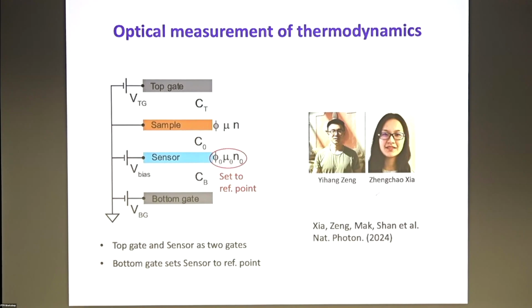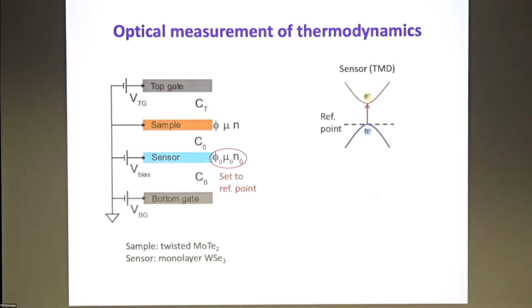In this kind of structure, we can think of the top gate and the sensor as acting as the top and the bottom gate to the sample. And the function of the bottom gate is to fix the sensor to a fixed reference point. Okay. And this is the work by these two people here. The sample is twisted MoTe2 here, and the sensor we pick is a monolayer tungsten selenide.